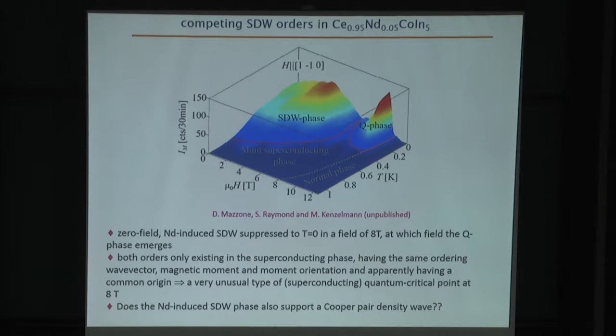Now we've seen that there is a field-induced spin density wave in the Q phase of pure cerium cobalt-5, and that replacing 5% of the cerium with neodymium also induces a spin density wave, in this case at zero field. So the logical question is, what happens if we apply a magnetic field to the sample with 5% neodymium? Michelle Kinzelman and co-workers have just recently explored this question, and their answer is summarized in this field-temperature phase diagram, where the vertical axis is the neutron scattering intensity.